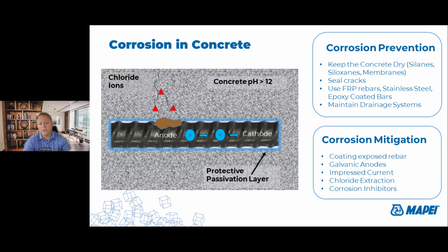The anode is losing electrons. So the electrons are flowing from the anode to a cathodic spot on the steel. It could be right next to it. It could be another mat down. In a lot of reinforced concrete, the steel is all tied together so the electrons can flow to where they need to go. And when this happens, the steel at the anodic region begins to expand, and steel can expand about 7 to 10 times its size, and that introduces additional tensile stresses in the concrete, and it causes it to crack, and then you have basically a path for more and more chlorides to get in.